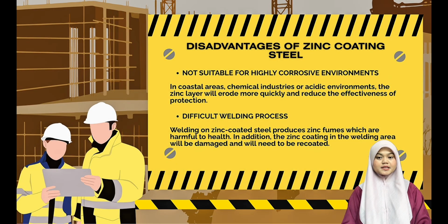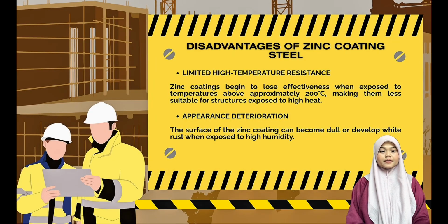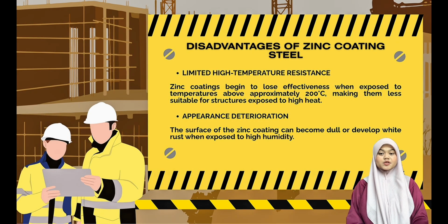Another disadvantage is the difficult welding process. Welding galvanized steel produces toxic zinc fumes, which can be harmful to workers if inhaled. Therefore, proper ventilation, safety equipment, and post-weld coating repair are required, making the process more complicated. The fifth disadvantage is limited resistance to high temperature. Zinc coating starts to lose its protective properties when exposed to temperatures above approximately 200 degrees Celsius. This makes it unsuitable for structures that are exposed to excessive heat or fire.